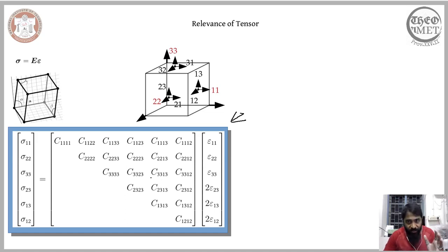This category of material has 2 crystallographic angles of 90 degrees. So it means my normal stress is now going to give me 2 zero shear strains. There are 2 shear strains that are going to be 0. Only one non-zero shear strain is going to pop up. Now such a material we refer to as monoclinic. The behavior of such a monoclinic material I will be able to introduce in this representation when I change certain entries of this matrix to 0.